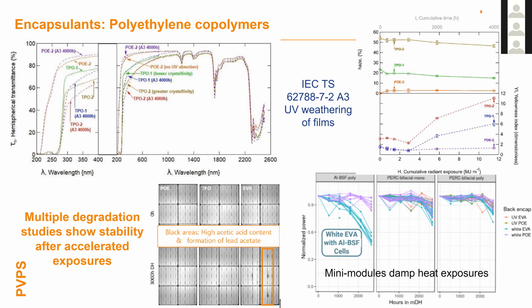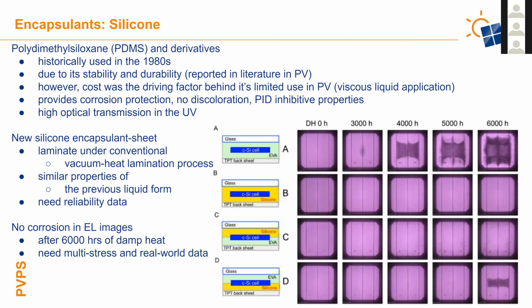Another type of encapsulant starting to be looked at again is silicones. PDMS and its derivatives were historically used in the 1980s due to its stability and durability, as reported in the PV literature. We also see in other areas that these silicones are pretty durable. However, there was a cost problem, so it had limited use in PV. It was applied as a viscous liquid, so it was hard to do in line and without as much cost. But it seems silicones provide corrosion protection, don't really have discoloration, and don't really have PID, and they still have high optical transmission in the UV region.